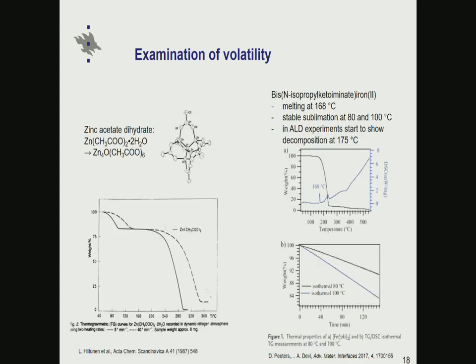For example, heating rate. We saw an example here. In this case, when heating was done at a slow rate, there was enough time for everything to evaporate before decomposition started. But if the heating was done 8 times faster, one doesn't get zero residue any more, because when reaching the temperature where decomposition starts, there is still quite a lot of material in the TG crucible, and decomposition starts to affect the result. So a slower heating rate gives a better result in that sense.